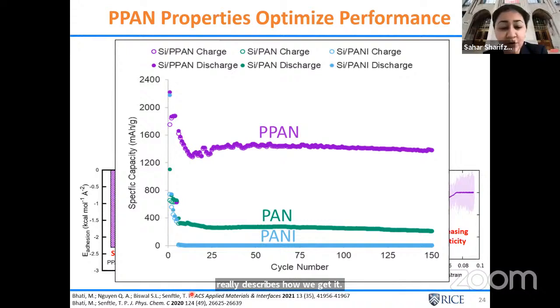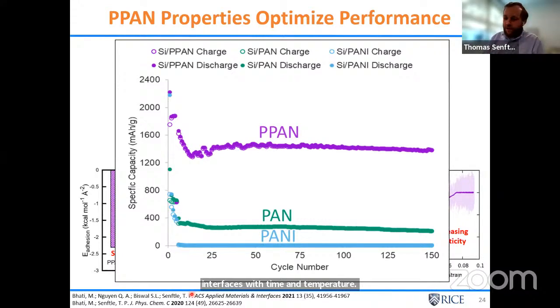And also, do you see silicon defect evolution at these interfaces with time and temperature? So we haven't looked at that. It would be hard. This is where even ReaxFF, being a cheaper computational method, doesn't get us all the way away from the problem of being limited to nanoseconds and being limited to still only a couple thousand atoms. So it depends on what defects we want to look at. We haven't investigated that, but in principle, we could look at it, especially if it's something like vacancies migrating around or surface reconstructions that happen at relatively quick timescales.